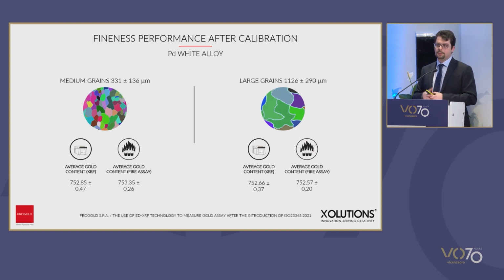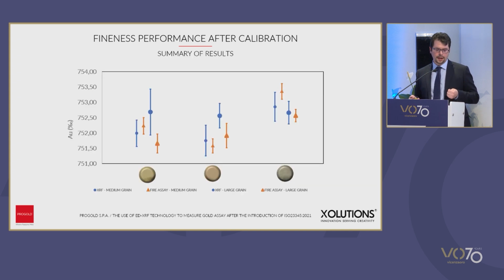And please consider that the fire assay regulation establishes that when you do repeated tests, values are acceptable if the difference is within half per mil. So we're very close to the results that have already been achieved. So we could also think that the results in this case are even better. And the limit of fire assay for palladium is that palladium doesn't dissolve so easily, and so you have to take